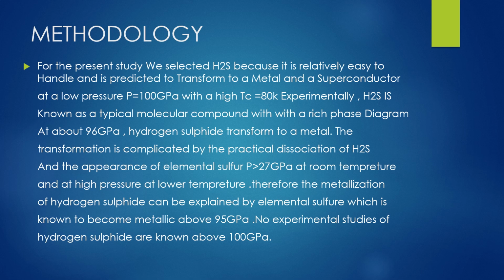P is greater than 27 gigapascal at room temperature, and at high pressure and low temperature. Therefore, the metallization of hydrogen sulfide can be explained by elemental sulfur, which is known to become metallic above 95 gigapascal. No experimental studies of hydrogen sulfide are known above 100 gigapascal. So basically, this is the methodology of making the superconductors.